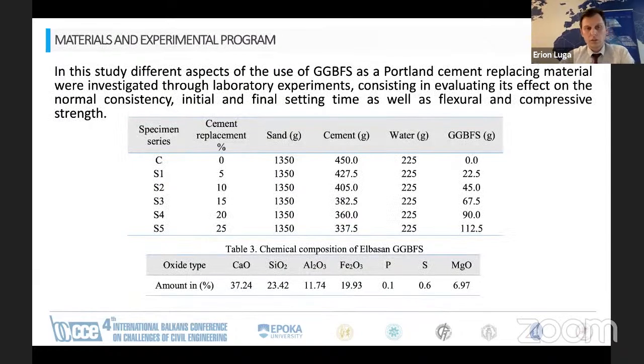So here there are two tables. The first one shows six different series of mortar mixes that are used during the investigation. There is an incremental increase of the amount of slag added in the cement, starting from 0 in the first one, which is the control specimen, then 5%, 10%, 15%, 20%, up to 25% replacement.